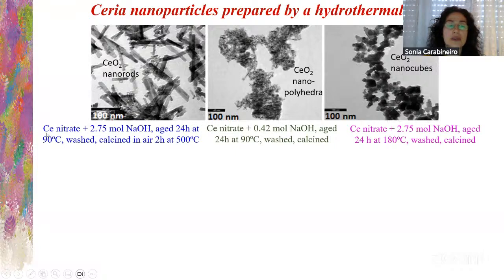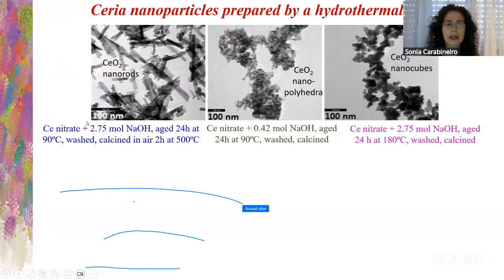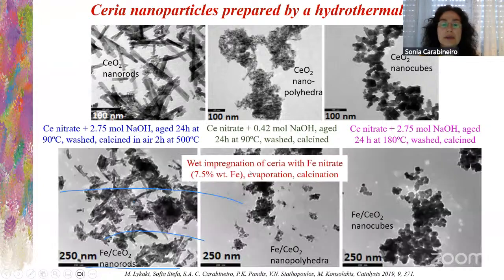So the nanorods were obtained with these conditions: 2.75 moles of sodium hydroxide, 24 hours, 90 degrees, calcined at 500 degrees. Okay, and if we use 0.42 moles sodium hydroxide, we obtain this nanopolyeder. If we increase the temperature, and this concentration is the same as in the nanorods, we obtain the nanocubes. Okay, so that is different.